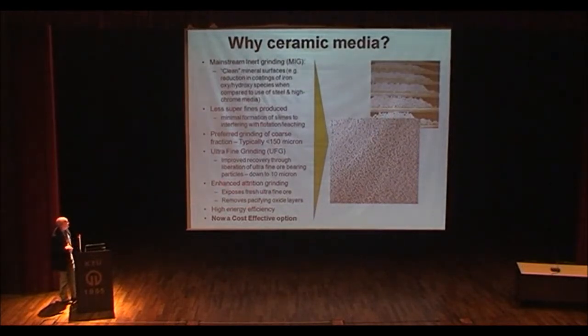And the other factor is here, and this actually goes together with mainstream inert grinding, is if, in a lot of instances, your stock material is on stockpile for sometimes for months, certainly for a few days, it can be wet, rain, whatever, you already get on the fresh sulfide faces an oxide coating, which again starts to passivate your sulfide. When it comes through into the mills, these very fine beads, you get a very much higher attrition milling, which is not a crushing, it's a grinding. It cleans the surfaces as the material goes through. So it cleans up the faces again, you expose fresh faces, you remove that passivating layer, again, you're in a better position to get maximum recoveries.